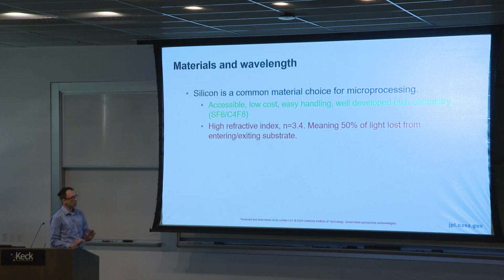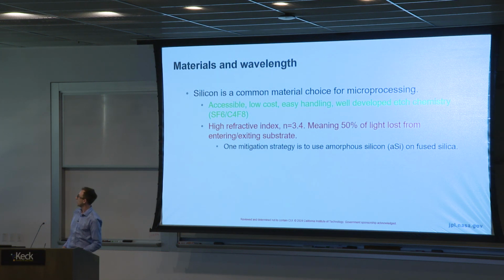So if you can tolerate that, great. But if you really want to collect more than 50% of the light, you have to address that somehow. One mitigation strategy, and you might recognize this combination of materials, is to use amorphous silicon on fused silica. Here you're still able to use silicon, but you've removed the wafer itself, so you never really enter and exit the silicon wafer. So you can improve on this number, because the fused silica wafer, I mean, just looking out the window, okay, they happen to be closed, but if they weren't, you know that you don't see a huge reflection of yourself in the window. So there's a way to mitigate this.